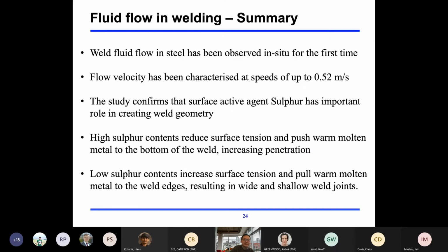So probably this is a quick summary of this fluid flow in welding. We said weld fluid flow in steel has now been observed in situ. When we did the experiment, we were the first group to do that. And flow velocity has been characterized at speeds of up to 0.52 meters per second. It's very dynamic flow in the weld pool. And the surface active agent sulfur has an important role in creating welding geometry.